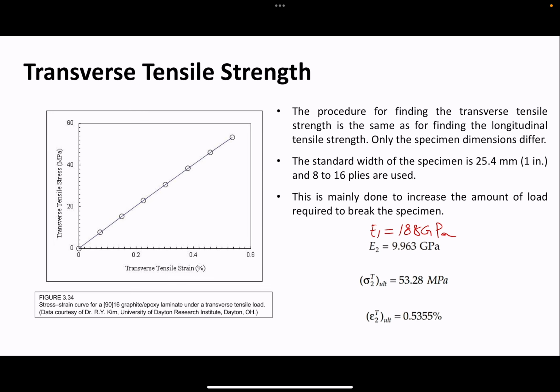Then we come to the transverse tensile strength, the third strength, which is tensile strength, normal strength. So sigma, transverse, direction 2, and then tension. So how do we find this? It's the same standard you followed for longitudinal tensile strength. It's the same specimen, I believe. The standard width of the specimen is 1 inch, and 8 to 16 plies are used. This difference is mainly to increase the amount of load required to break the specimen. Meaning, usually in the transverse direction, the properties are very, very low compared to your longitudinal direction. So that's why you make it thick so that immediate failure doesn't happen. That's all. So 8 to 16 plies are used, but it follows the same tensile specimen.